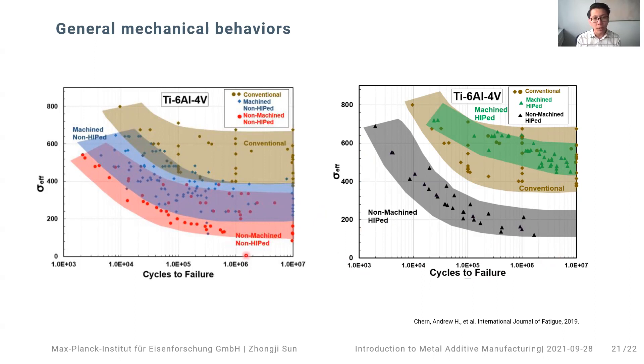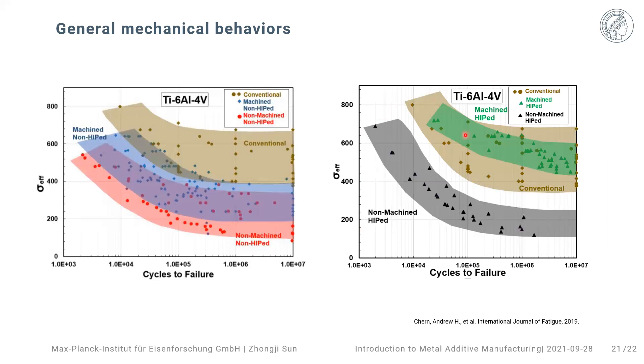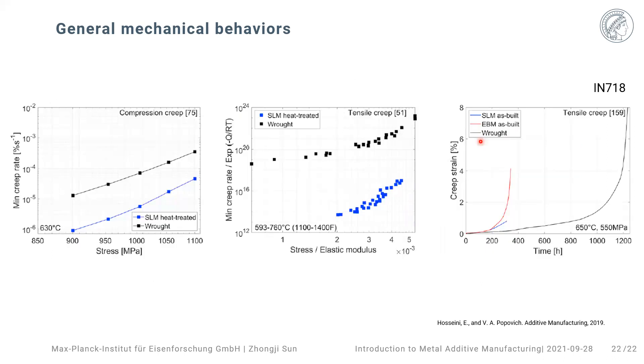AM-built parts have a lot of surface roughness — what we call surface defects — and if the laser or electron beam parameters were not well optimized, there can be a lot of internal pores that serve as crack nucleation sites. If we take a part directly out of the 3D printer and do a conventional fatigue test, it lags far behind conventional counterparts. If we just machine away the outer surface to remove surface defects, the property increases slightly. The only time you get somewhat comparable fatigue properties is when you remove both the surface roughness and internal porosities.